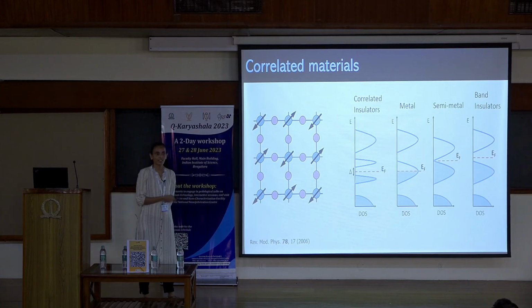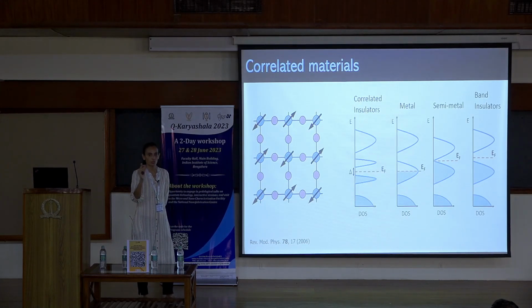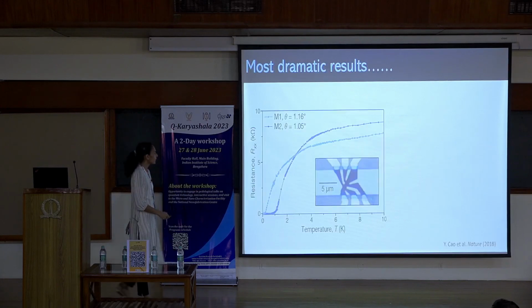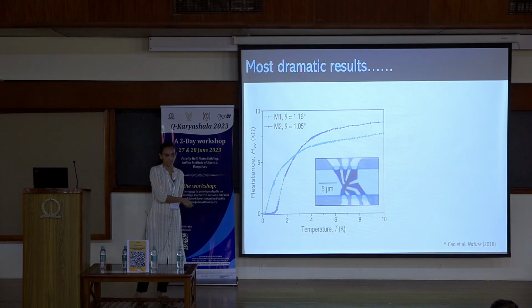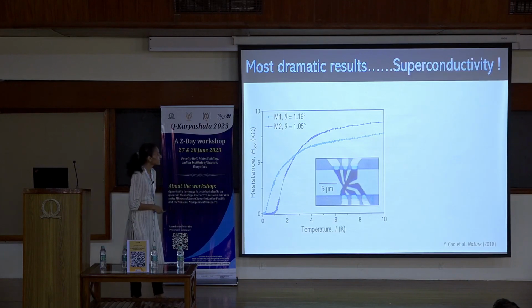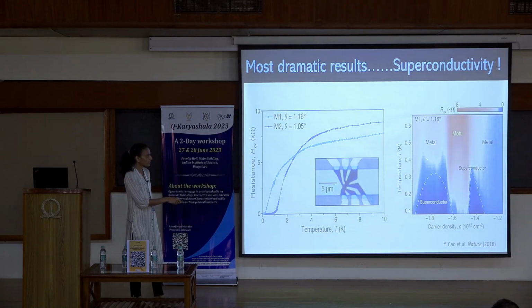Now the interesting part is that graphene also shows this. Graphene, which is a very simple material, also has correlated phenomena that come in only because you have twisted this material with respect to another single layer, and that doesn't behave like graphene anymore. The band structure has completely changed. Okay, that was not all. The most important discovery was that this also shows superconductivity. Now a material that shows superconductivity is usually very sought after. So this particular material shows superconductivity. It's a metal at some higher temperature. It's an insulator. It's called Mott here, but it's basically that insulating state that I talked to you about.